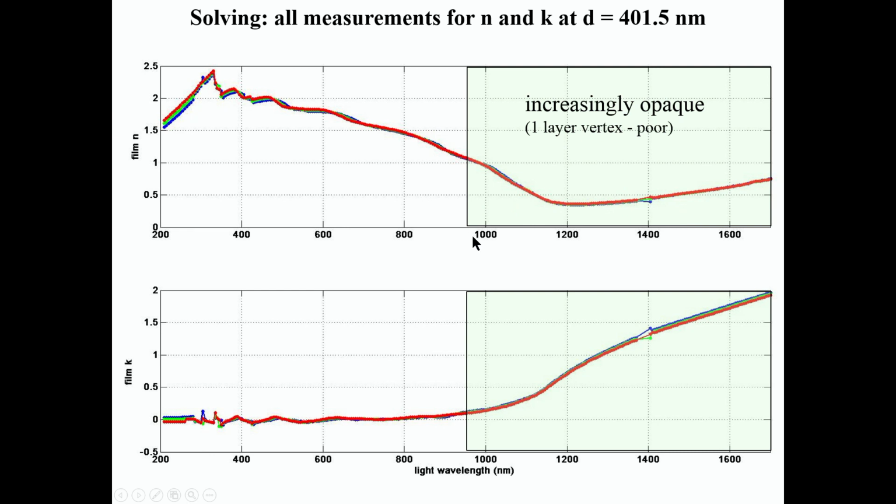So in this region here, from about 950 out in wavelength, you'll see something interesting if you take a look, first of all, at the curve for K. So you can see that this line is K equals 0, so over here it's transparent, but over here it's not, it's absorbing. And these numbers of K, 0.5, 1, 1.5, 2, are characteristic of a metal. So it has a metallic behavior optically for that range of wavelengths.